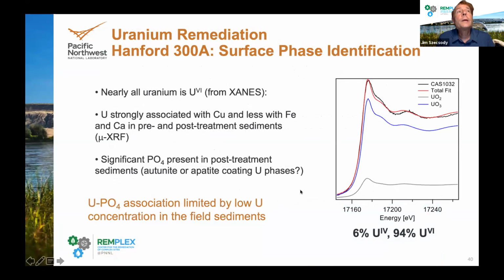Because uranium concentrations were actually kind of low in the Hanford 300 area, we were able to identify some surface phase components, but not everything. Shown in the diagram on the right side here is the XANES analysis, which gives us oxidation state, and most of the uranium was U6. We know that we formed a considerable amount of phosphate precipitates, but we were not able to identify what exactly the uranium phosphate association was. Did we form autunite, or was the apatite simply coating uranium surface phases? So we were limited in that with these field sediments.